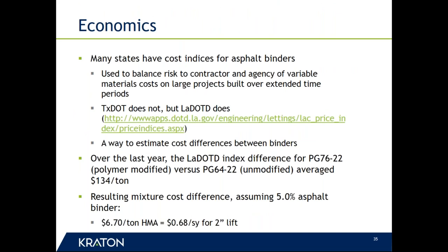Questions always come up about economics. And so probably the best way to get an apples to apples comparison is to simply look at things like a cost index. TxDOT doesn't maintain a cost index for asphalt binders, but Oklahoma and Louisiana do. And the nice thing about the Louisiana DOTD index is that, for one thing, they have some common suppliers with TxDOT, but also they have different indices for different binder grades. So they have ones for 64-22 and polymer modified grades. If we look at their index, and you can easily get that from their website, the difference in the binder cost between PG 76-22, which is the most common polymer modified grade specified, and PG 64-22 was $134 a liquid ton. What does that translate into mixture cost?